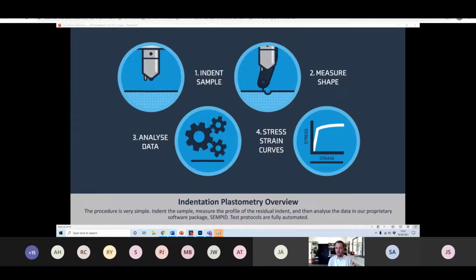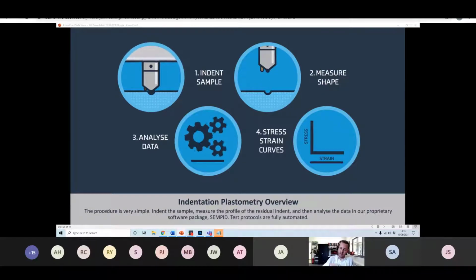The first is that, as we saw in the video, we indent the sample. The difference at step 2 between that and hardness testing is that we measure the full profile shape. And we do that because we know, as I mentioned, that the full profile shape contains an awful lot of information about the way in which the material is deformed, and therefore an awful lot of information that can be used to back out or infer the underlying stress strain behaviour. And to do this in our software package, we analyse and operate purely on the residual profile shape, nothing to do with the load displacement curve. And we have this algorithm which returns the stress strain curve very quickly.